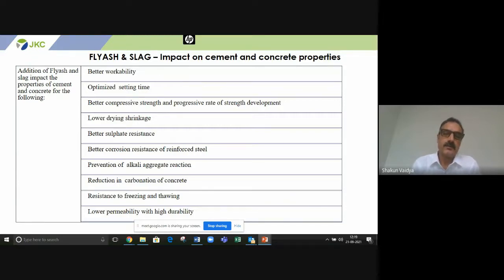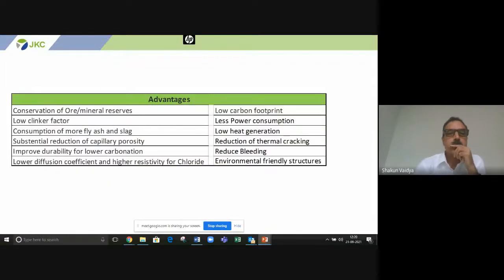So yes, we need to make the concrete more and more impervious and lower the permeability of the concrete as much as we can, because in the absence of capillaries and pores, the embedded steel would be corrosion free for many, many years. So low carbon footprint, less power consumption, low heat of hydration, reduction of thermal cracking, reduced bleeding, environmentally friendly structures, all can be achieved with blended cements.